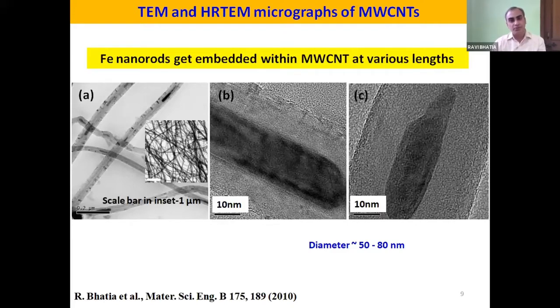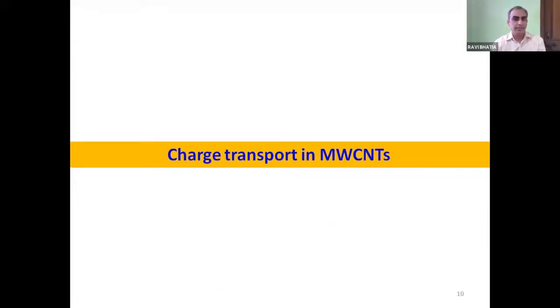I apologize for not showing you the XRD of this sample, in which clearly the iron peak appears, because I thought it is going to be a 2-hour lecture, so I thought we cannot provide all the details. However, this particular HRTEM provides an estimate of the diameter of these tubes, which lies in the range of 50 to 80 nanometers. Now I will be talking about charge transport, and it is going to be a low temperature charge transport property. Low temperature means we are going to decrease the temperature from 300 Kelvin to something like 4.2 Kelvin, which can be achieved by liquid helium.